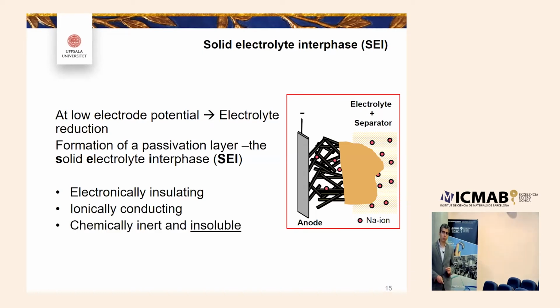Another important aspect, sometimes neglected, is the solubility of this SEI. You form this SEI at the cost of irreversible capacity at the beginning when you start the battery. It forms via irreversible charge—you consume electrons and electrolyte to form this layer. It needs to be very stable because you don't want to form it again, meaning it should not dissolve in the electrolyte.